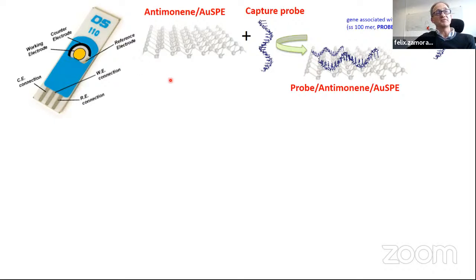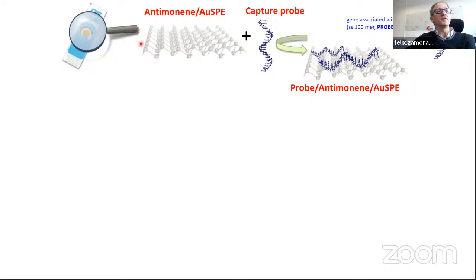What we try to do in here, we construct our sensor using again this SPE device. So in here we have the screen printed electrode, but in here we work just with gold instead of graphite, as in the case that I showed you before. So the working electrode is gold. Then on top of this gold we put the antimonene, and then on top of the antimonene, we locate what we call a capture probe, which is this sequence of single-strand DNA, composed of 100 DNA nucleotides.